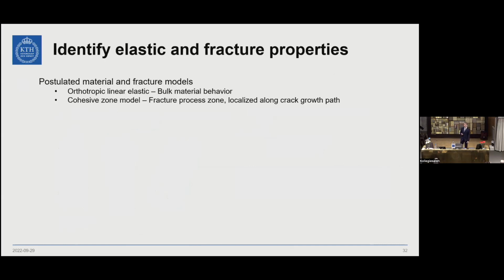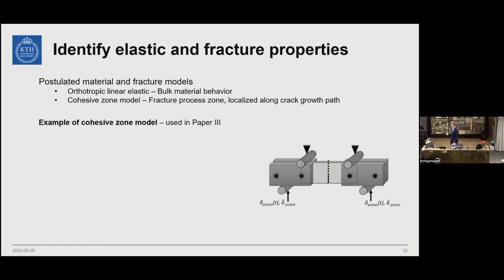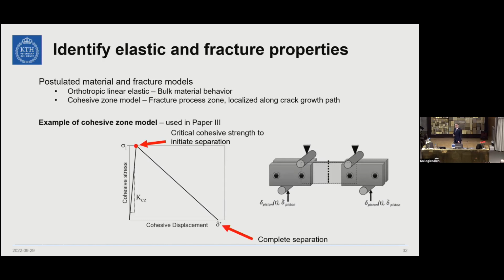So to identify the elastic and fracture properties, we need to postulate material models. So we postulate a linear elastic orthotropic behavior, as we learned before in the tensile test, and then a cohesive zone model to model the fracture process zone. An example of that is in the weakest direction, where the crack is growing along the fiber direction, used in paper 3. The cohesive model is basically initiated when the stress level at the crack tip reaches a critical cohesive strength. And this is where the cohesive zone is separating the surfaces, until there is a complete separation where it fails. And the area under this model is basically the fracture energy that is dissipated.